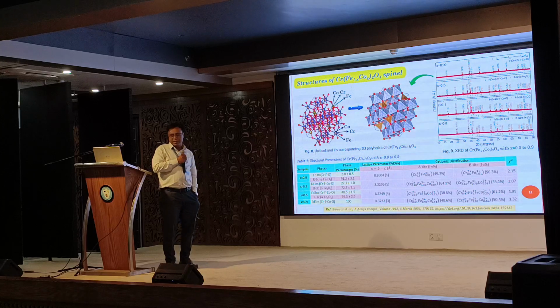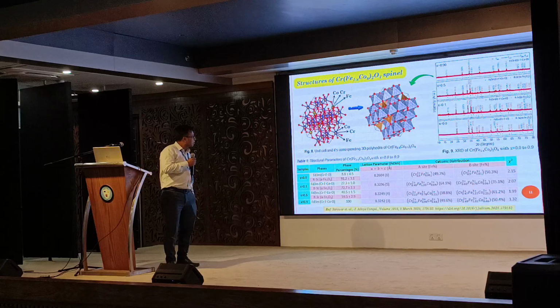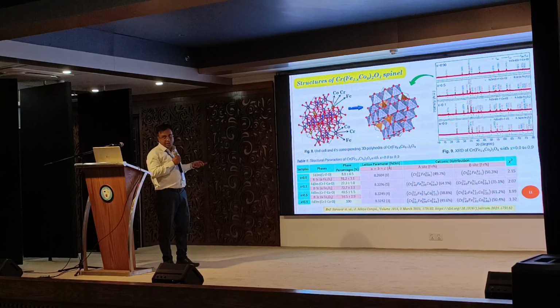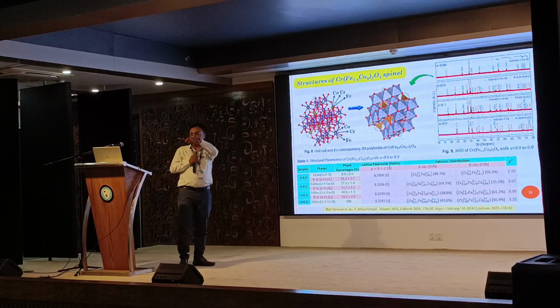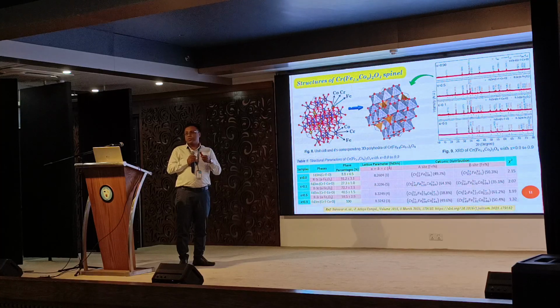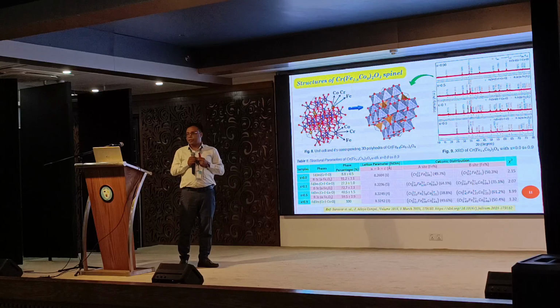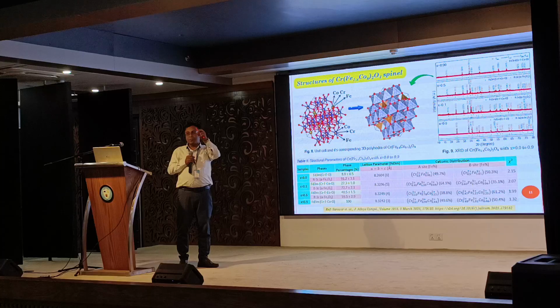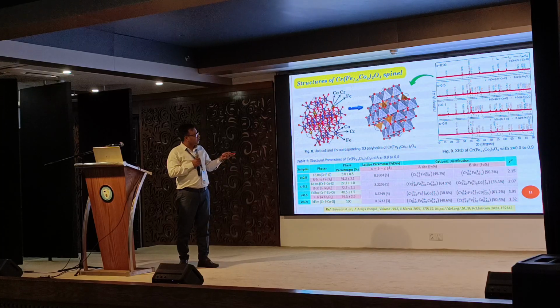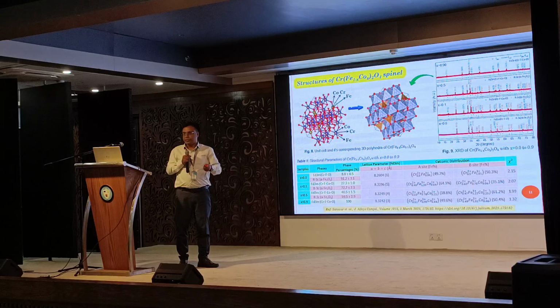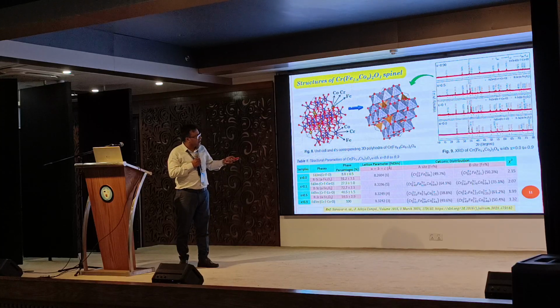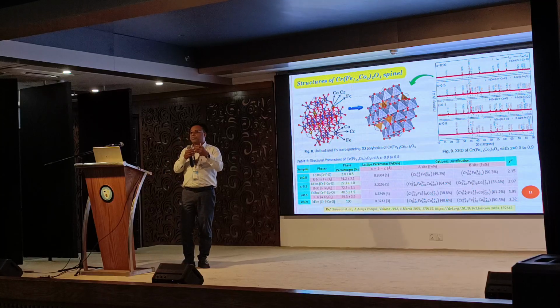Okay. So primarily I found the structure of it as a mixed spinel here. It is confirming a mixed spinel structure. But how did I get this? Here, I think CSE students are here, computer science students. You can use the FullProf software, by Rietveld refinement and cationic distribution, where the atoms sit. Then here you see the data: the red dots are the experimental data and the black line is the simulated data. This simulated data came from the equation, and the blue line shows the difference between the red dots and the simulated, calculated black line. This ensures how perfect your simulation is.